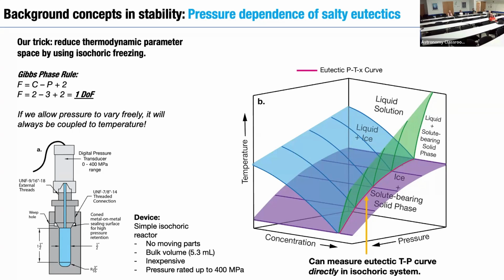So if we think to Gibbs phase rule for a second, in a binary system, we have one intensive thermodynamic degree of freedom, right? So this means that I can change either temperature or pressure for a given univariate state. I can't change them both. And practically, what this means for us doing isochoric freezing is that if we confine the volume of the system and allow its pressure to respond instead of controlling its pressure, then we can only change the system's temperature and the equilibrium pressure will emerge, right?